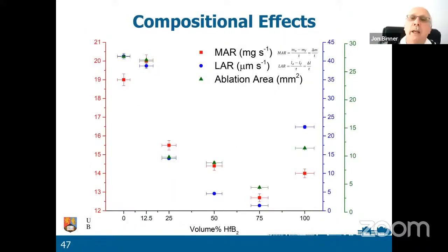And then the final thing is just to show you that this was an amazing discovery we made a couple of years ago. And this is the amount of hafnium diboride. So this is mixes of hafnium diboride and zirconium diboride. And you can see these are the mass ablation rate and the linear ablation rate.